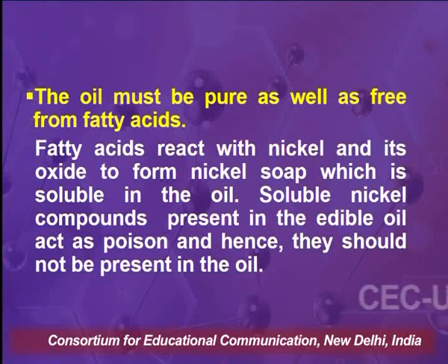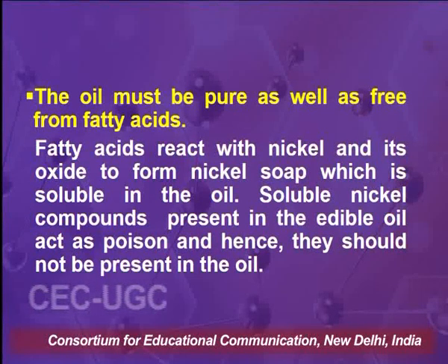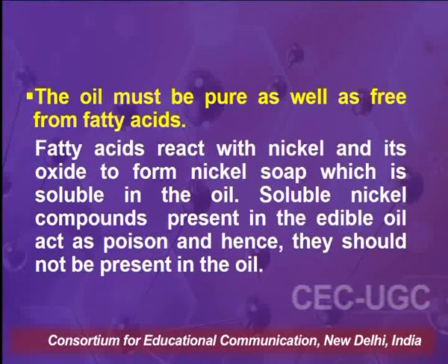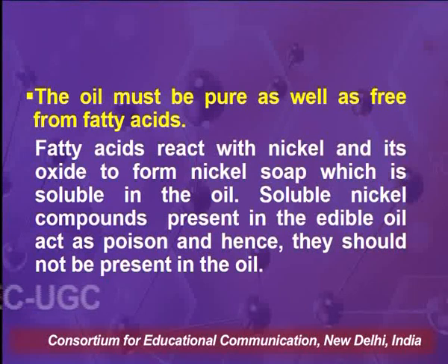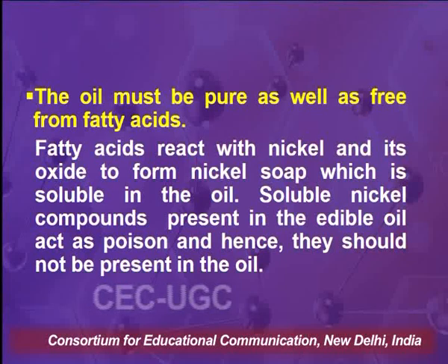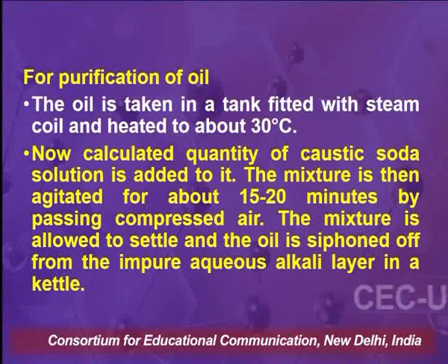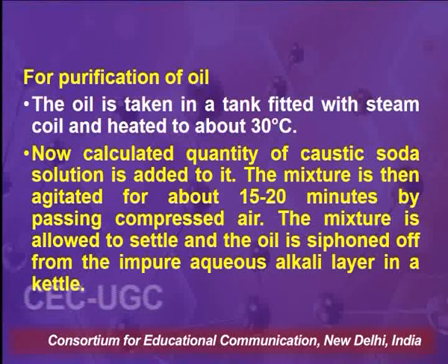The second point is that the oil also must be very pure as well as free from fatty acids. Fatty acids react with nickel and its oxide to form nickel soap, which is soluble in the oil. Soluble nickel compounds present in the edible oil act as poison and hence they should not be present in the oil. For purification of oil, the oil is taken in a tank fitted with steam coil and heated to about